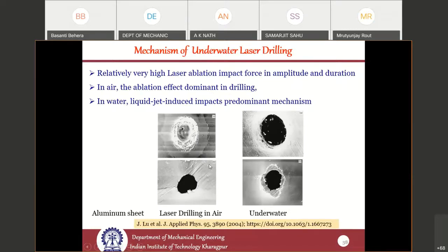In one of the experiments, they tried to see what the mechanism is. The mechanism in laser drilling in air is actually melting, vaporization, and ablation. But here it has been seen that in addition to these effects, you have a lot of liquid jet induced impacts, which also remove the material and help realize the cutting. So the process becomes much more efficient.